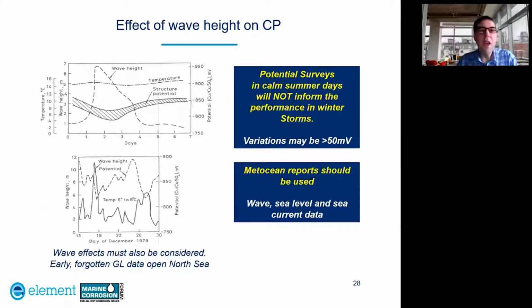Now I want to look at the effect of wave height on the cathodic protection system. You can see here that as the wave height increases, the potential on the CP system decreases. This is also shown on this graph from 1979, which shows that with high wave height action, you get a reduction in the cathodic protection potential. This means that any potential surveys on calm summer days will not inform the performance of the CP system in winter storms, and the variations may be greater than 50 millivolts. So it's wise to use Met-Ocean reports to look at the wave, sea level and sea current when designing your cathodic protection system.